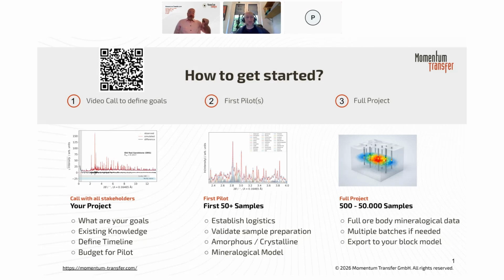The next step would be that you send us 50 samples, and it depends on the first pilot, but we would want to have something between 5 and 10 grams. Don't think boulders, and don't think micrograms yet, or milligrams. Yeah, 3 orders of magnitude. Milligrams. So then, with the first pilot, we establish the logistics, we validate our sample preparation. That's what Max talked about. How fine do we have to mill it? Do we have to mill it at all? We want to see how much amorphous versus crystalline is there, and then we want to build our mineralogical model.